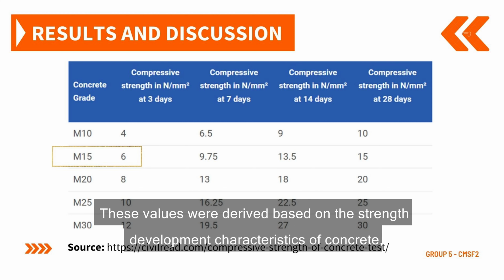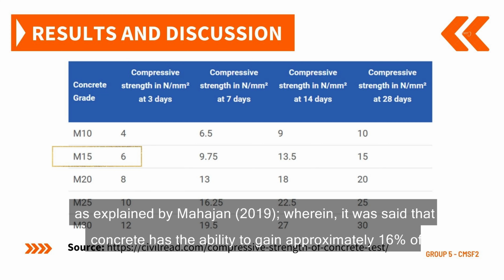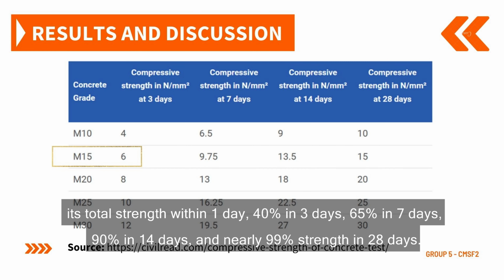These values were derived based on the strength development characteristics of concrete as explained by Mahajan 2019, wherein it was said that concrete has the ability to gain approximately 16% of its total strength within 1 day, 40% in 3 days, 65% in 7 days, 90% in 14 days, and nearly 99% strength in 28 days.